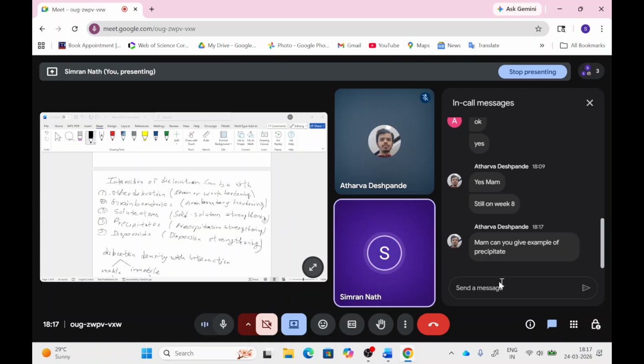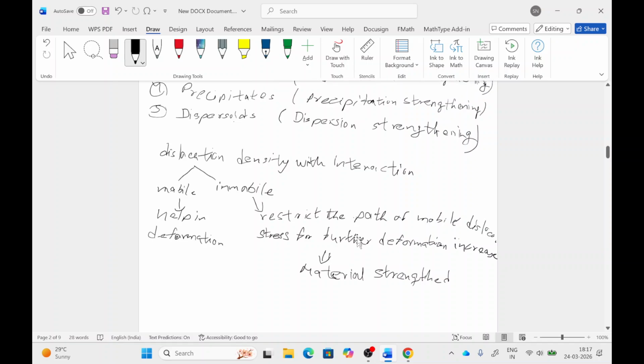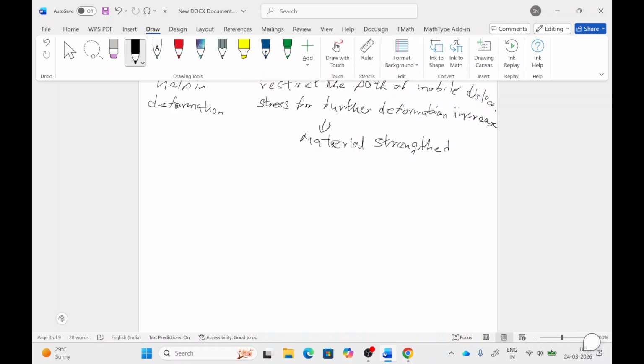I will give the precipitate example. The precipitates are intermetallics, meaning when two metals combine, that results in a precipitate. If we talk about the aluminum copper system, aluminum having 4 weight% copper, it is generally the 2000 series alloy. So the intermetallic from this system is Al2Cu. Two aluminum atoms combine with one copper atom to form an intermetallic. This intermetallic particle is called a precipitate.